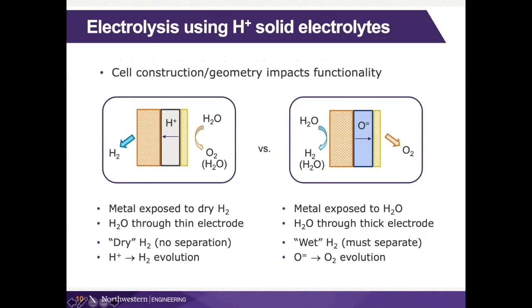So in the electrolysis mode, we bring in water to the air electrode. And what's nice here is that this is very thin, so you don't have mass diffusion losses. The other aspect is that the nickel, the fuel electrode, is on this side. So the nickel is never exposed to steam. In the case of the oxygen ion conducting electrolyte, the nickel is exposed to steam.